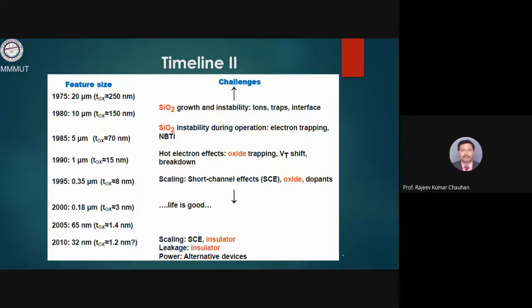So from 1975, when you had 20 micron dimension, by 1980, 85 we found that the dimension had gone to 5 micron. And from 1990 onwards, your oxide thickness had gone to 15 nanometer, or you can say 150 angstrom. So people started thinking about what to do when the continuous shrinkage of channel length goes on, because with oxide thickness less than 50 angstrom, as everyone knows, hot carrier effects, degradation in the oxide, trapped charges and interface states are going to trouble you. And short channel effect, as you can see on the right side of the slide, is going to increase from 1995 onwards.